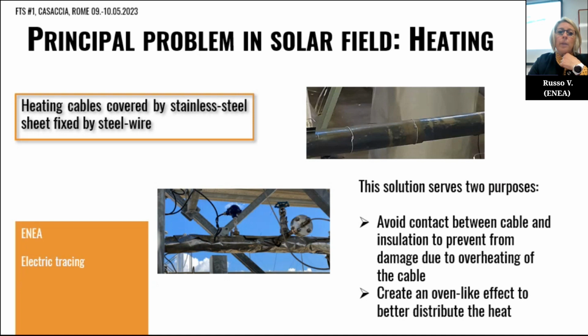Generally, the cable must be covered by a stainless steel sheet. This solution avoids contact between the cable and the insulation, in order to prevent damage from overheating of the cable itself. And also in order to create an oven-like effect to better distribute the heat along the pipe or along the component.